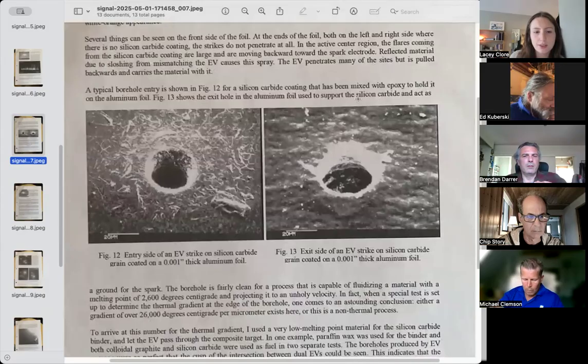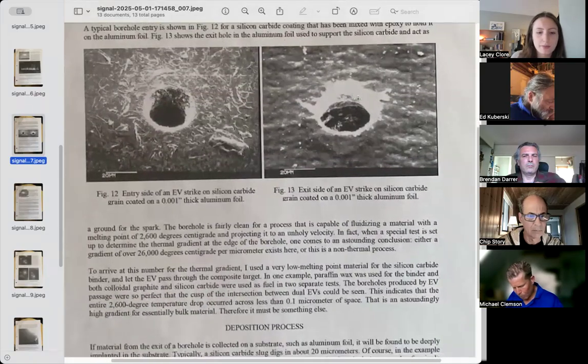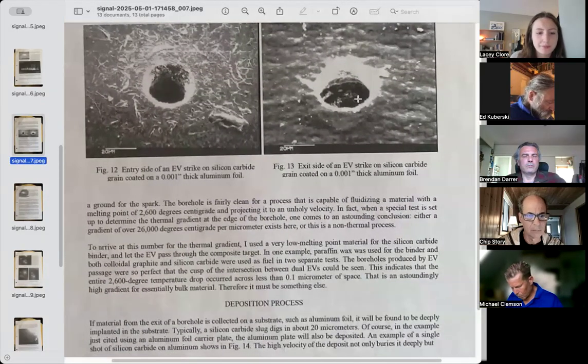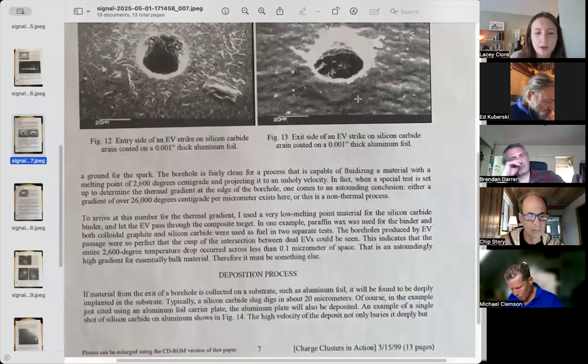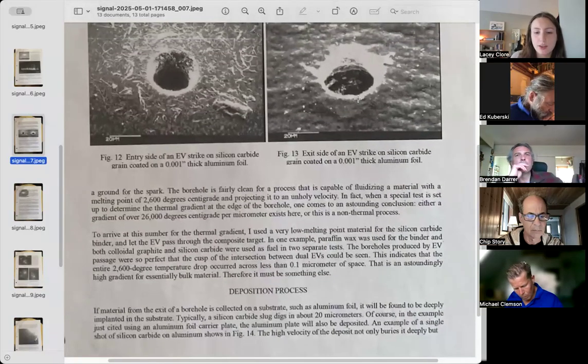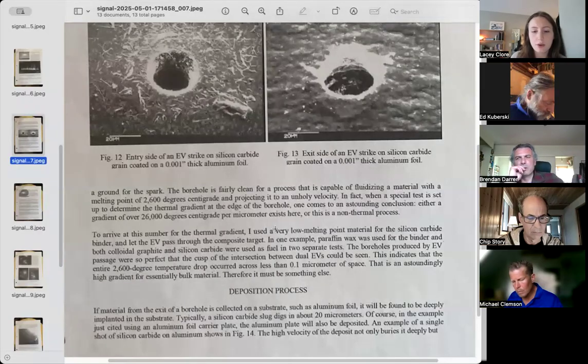Figure 13 shows the exit hole in the aluminum foil used to support the silicon carbide and act as a ground for the spark. The borehole is fairly clean for a process that is capable of fluidizing a material with a melting point of 2,600 degrees centigrade and projecting it to an unholy velocity. In fact, when a special test is set up to determine the thermal gradient at the edge of the borehole, one comes to an astounding conclusion. Either a gradient of over 26,000 degrees centigrade per micrometer exists here, or this is a non-thermal process.